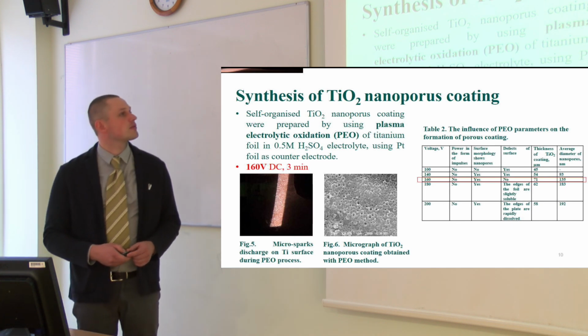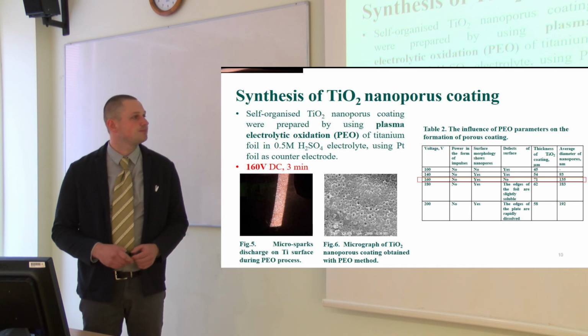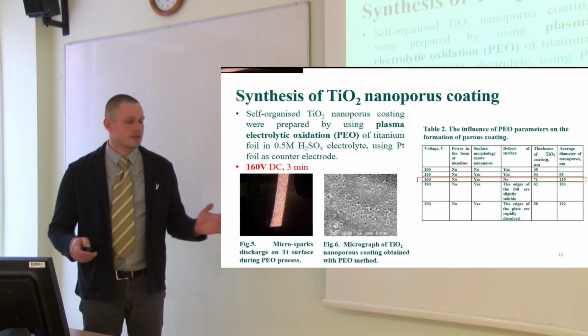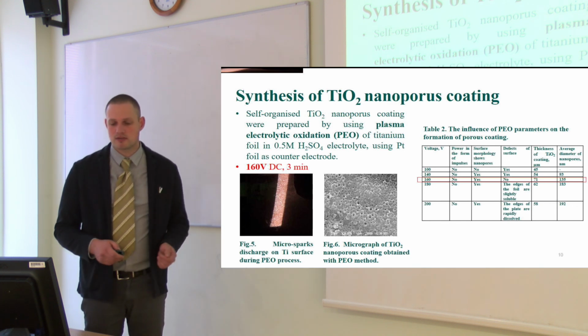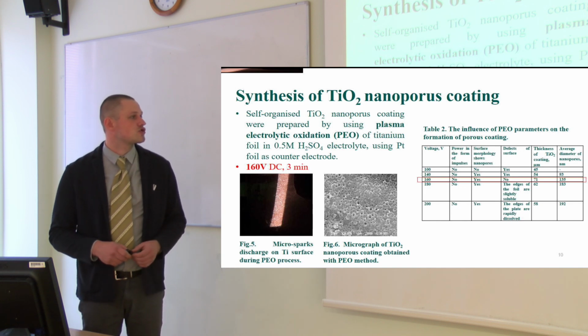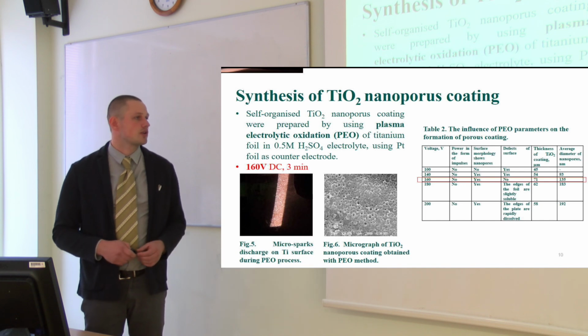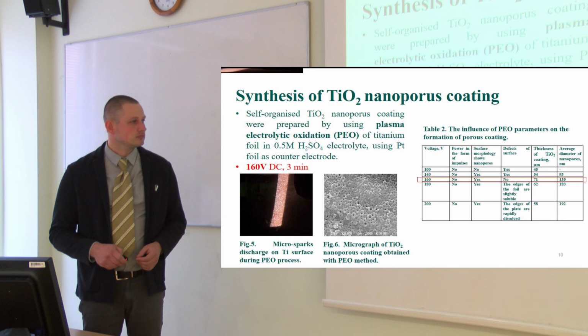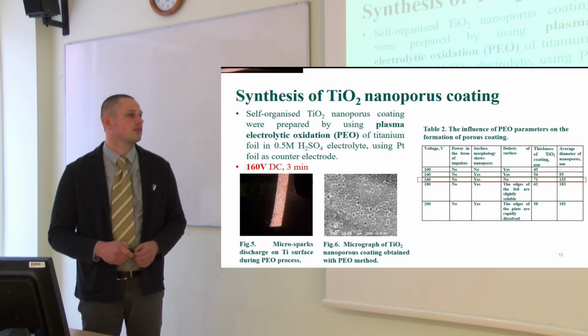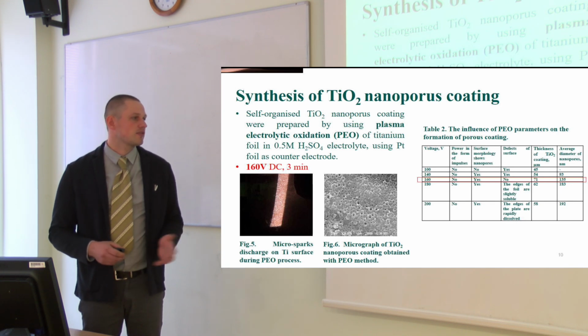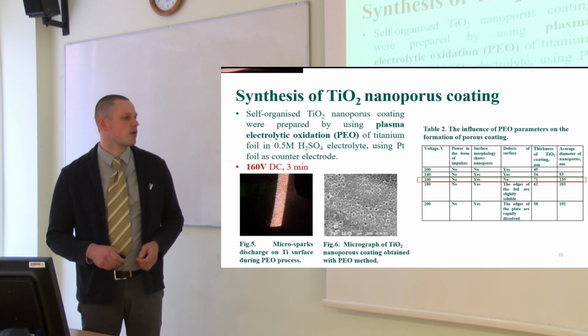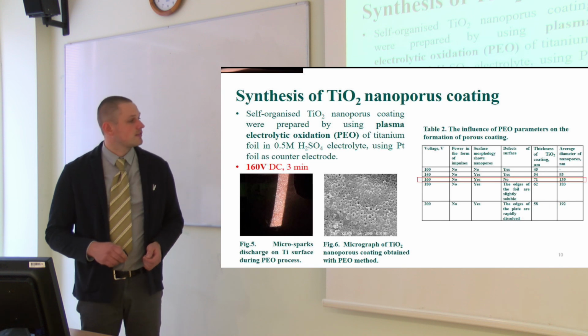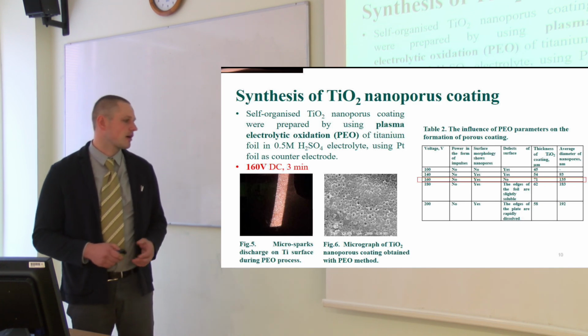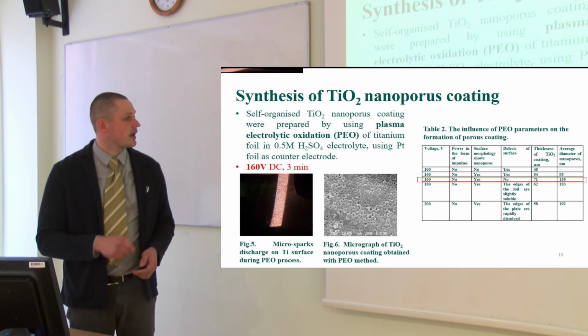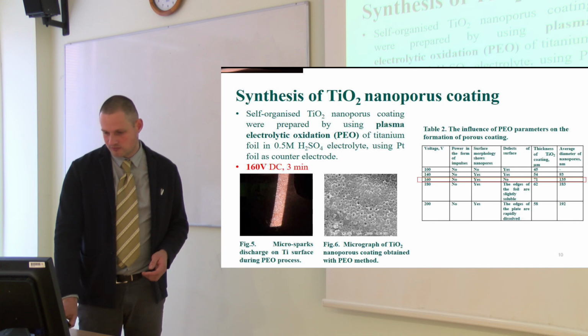The next method was plasma electrolytic oxidation method. Also we use titanium foil. The setup is quite similar to the anodization method, but we use much higher voltage, and the experimental time is much shorter. So we have noticed that when we choose 160 volts, we can obtain the best quality of such titanium dioxide nanoporous coatings on the surface of titanium. And in this picture you can see small sparks, spark discharge during this microplasma electrolytic oxidation process. It is the titanium electrode covered with such sparks.